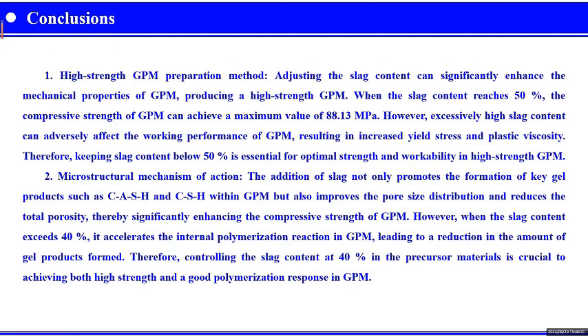However, excessively high slag content can adversely affect the working performance of GPM, resulting in increased yield stress and plastic viscosity.